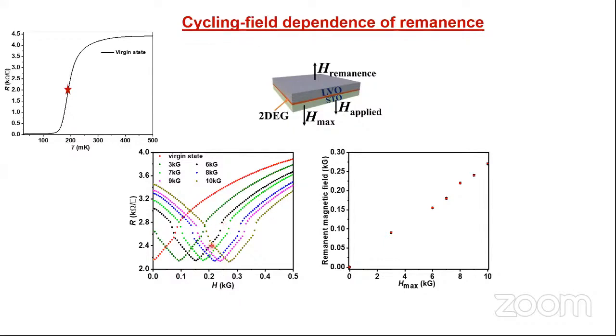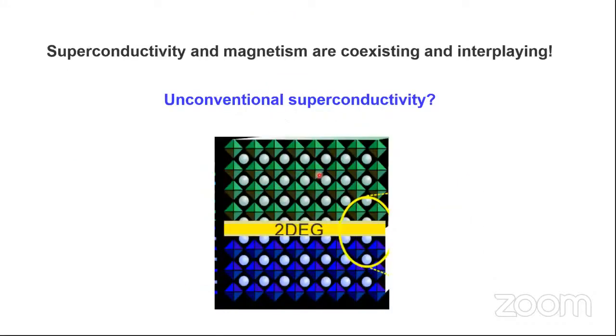So that means by doing this kind of experiments, looking at the superconducting properties, we can also read the magnetic information that was written in the normal state. Now, we can see that superconductivity and magnetism are coexisting and interplaying with each other. So is it possible that this is actually coming from unconventional superconductivity?